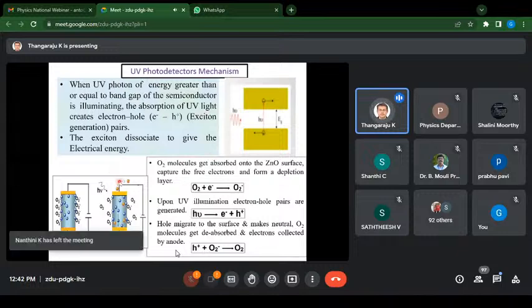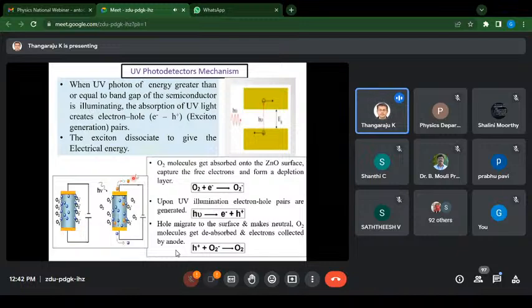So this is the typical working mechanism of these UV photo detectors. In the most widely used UV photo detectors, zinc oxide, an inorganic material, is combined with different organic molecules in our studies. This is the typical working mechanism. You can see that when the UV light is falling, there is a dissociation of the oxygen adsorbed onto the surface, and hence there is a flow of charges through the UV photo detector device.